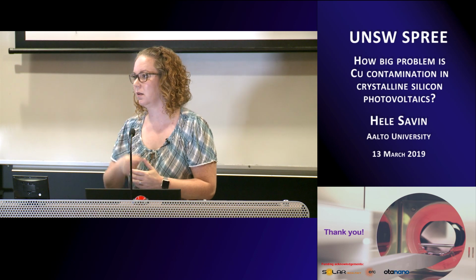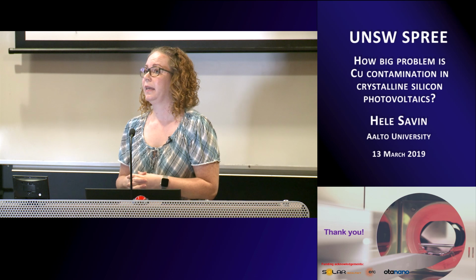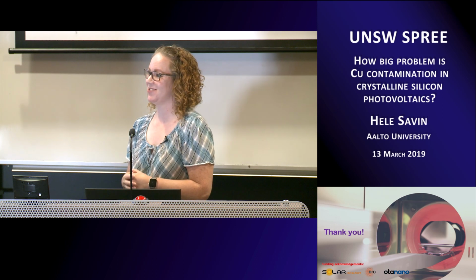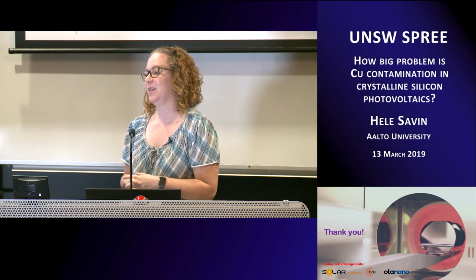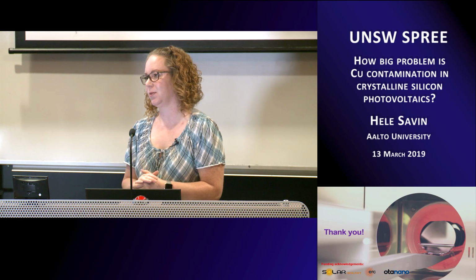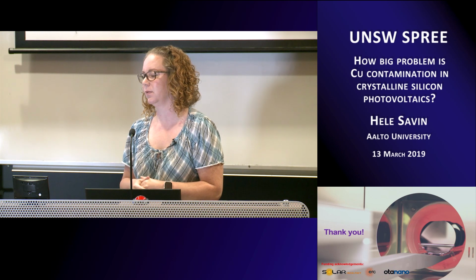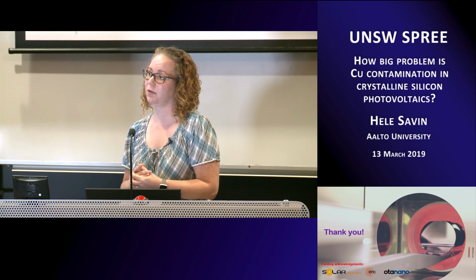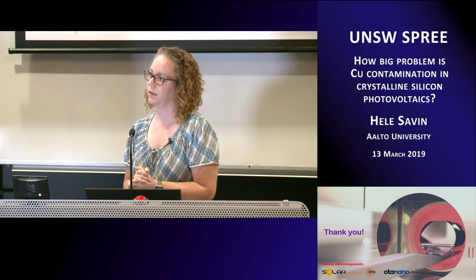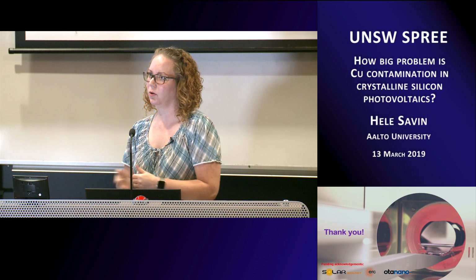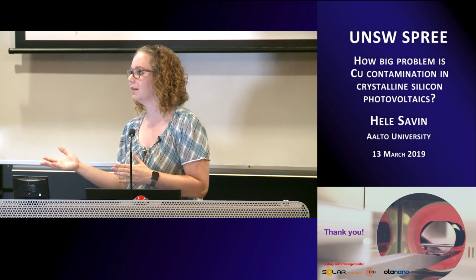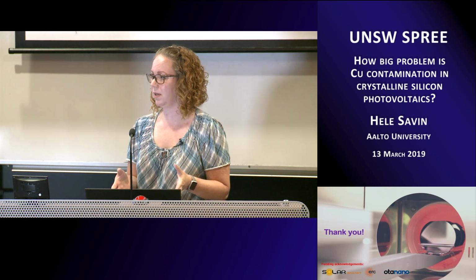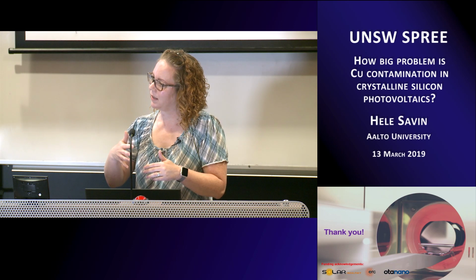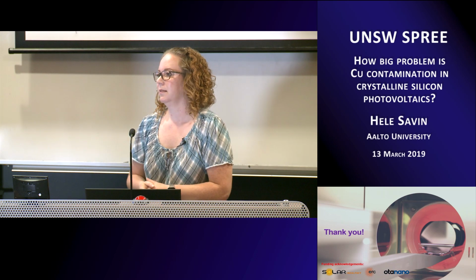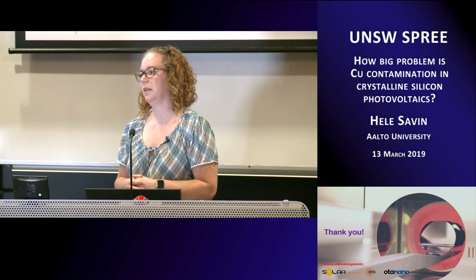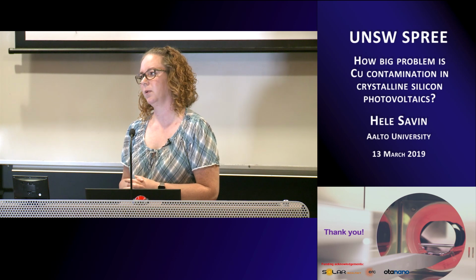So was this done in partnership with the company? Yeah. So they were quite happy putting those wafers in? Yeah, I had the same discussion here. Can I put my wafers into the equipment? But we are talking about much lower concentrations than are typically even present in multicrystalline silicon. So the concentrations are really small, and it's really not diffusing outside or contaminating more than what they already are. We do all these experiments in a very controlled environment in a high quality clean room, and after contamination our lifetime is still 10 milliseconds, so we are not contaminating the equipment.